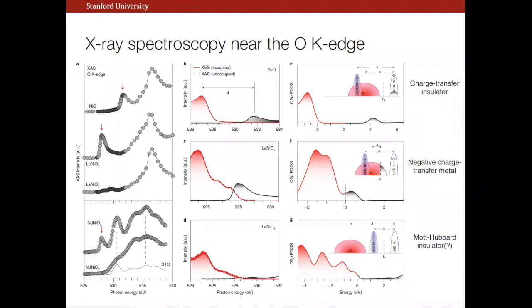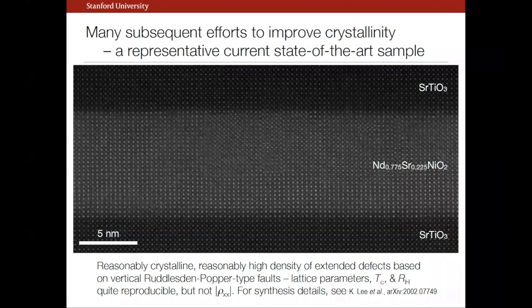And speaking specifically of this singlet issue, you can see here this oxygen feature that's prominent in nickel oxide or the nickelate, the Ruddlesden-Popper, is vanishingly small for the infinite layer phase. So cool.